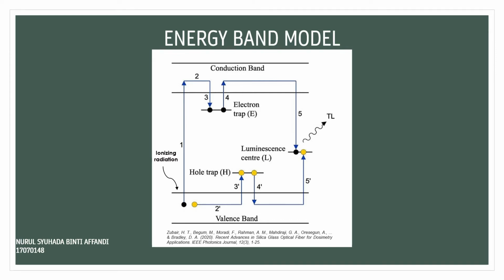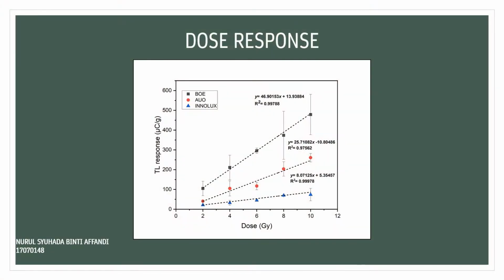Recombination is a process where the electrons combine with the holes at the luminescence center, also known as the emission center. And from the glow curve, we can obtain dose response, sensitivity, linearity index, and fading. And this is what I'm going to elaborate further. So, first is the dose response. Dose response is important to see the linearity. It is proven that these 3 types give linearity and the R-square values are above 96%.